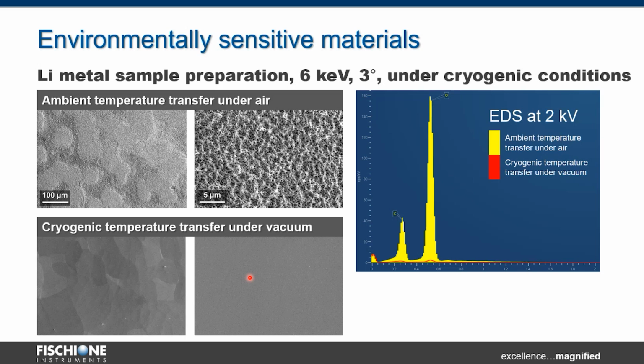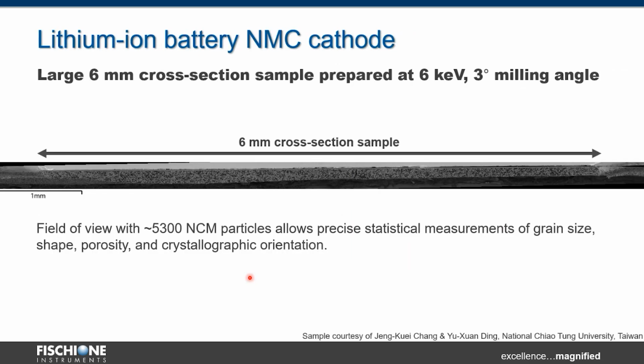SEM image of the lithium metal surface. So the application for that is, of course, the development of lithium-ion batteries. So here we have an example of a large cross-section, a large 6 millimeter cross-section, and this large cross-section is the NMC cathode. There are small particles, and you can count them over that area. You can have over 5,300 particles for robust statistical analysis, and that's what you need in your research.